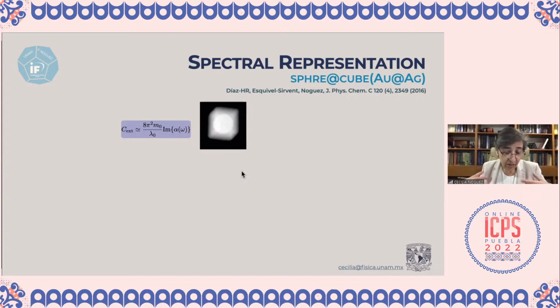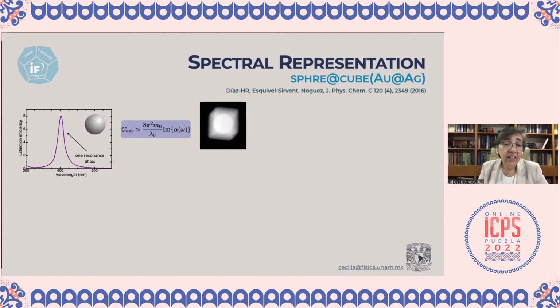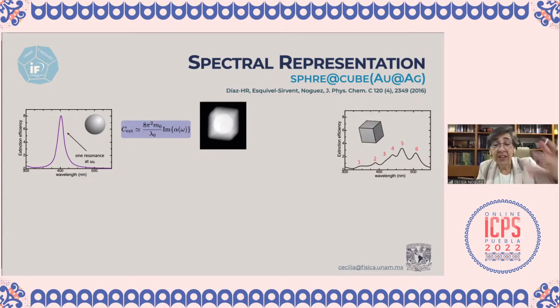So we have developed what we call a spectral representation, where we separate the contributions of both, and we try to understand if we can use this spectral representation for, for example, this kind of systems where people can grow a spherical particle inside of a cube. Okay, this is a real image made by a microscope. So these are real images of real nanoparticles. And now let's say that we have one resonance because the sphere has one resonance, versus 6 resonances because of the cube that has these 6 resonances.